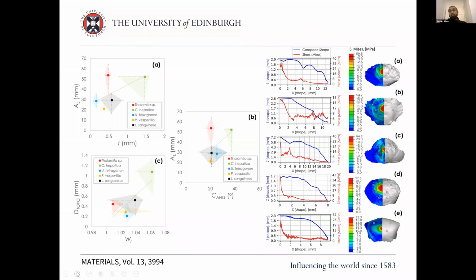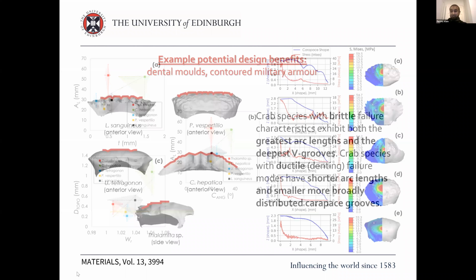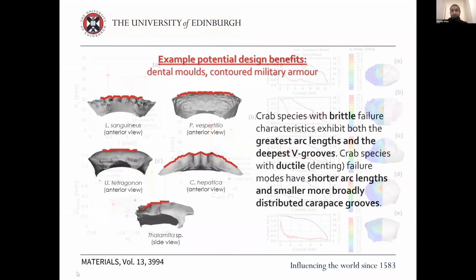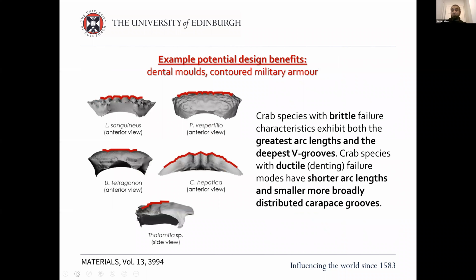Anyhow, in summary, crab species with brittle failure characteristics exhibit both the greatest arc lengths and the deepest V grooves. Whereas if you want ductile denting failure modes of a brittle material, then you need to have shorter arc lengths and smaller, more broadly distributed carapace grooves. And these are very different to corrugated plastics, which are ductile materials. Corrugated plastics will work well in impact because they can deform a lot, but these are brittle materials. So the application areas are different. You could get inspiration for application in dental molds, contoured military armors, and that kind of stuff when it comes to these types of structures.